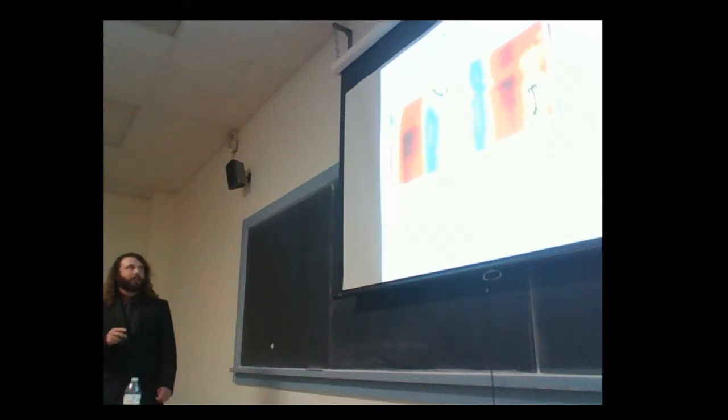So this is the picosecond decay associated spectra, and this is for the nanosecond. If I do very low fluence measurements at multiple temperatures and make a heat map with it, this is the folded Se 4p valence band. This is also the signature for that as well. But if you notice, at the phase transition temperature at 200, you still see optical signatures of the CDW phase, even much above the phase transition temperature.